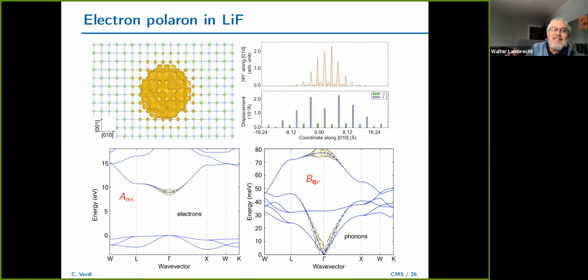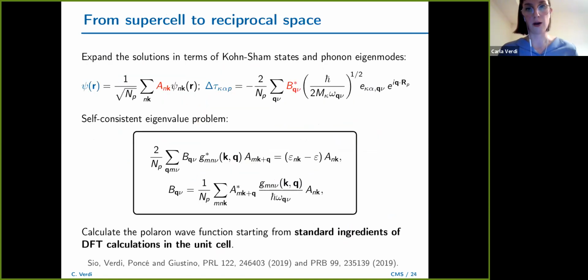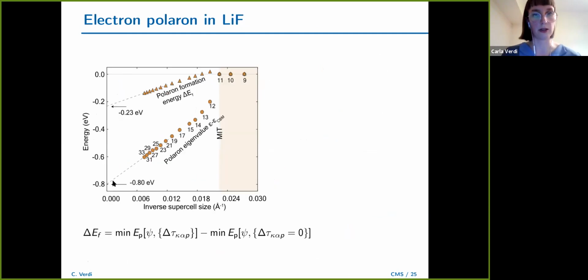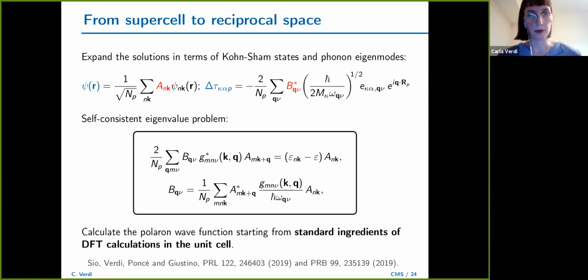Maybe I'll ask a question while we see if other people come up with questions. When you add this extra electron, how do you deal with the electrostatics? Do you have to put in a compensating background? In the derivation, you will see that we did put a compensating background, yes. But in our actual calculations, we don't explicitly put an extra electron in a supercell. We actually solve these equations, which simply include ingredients that come from density functional perturbation theory without explicitly adding any extra electron. But then, for example, we have this spurious polaron interaction that gives this linear dependency of the energy, and so you need to extrapolate. But in practice, when we solve our polaron equation, we never add explicitly an electron, so we don't need to deal with electrostatics.